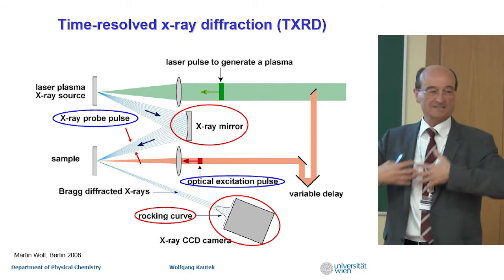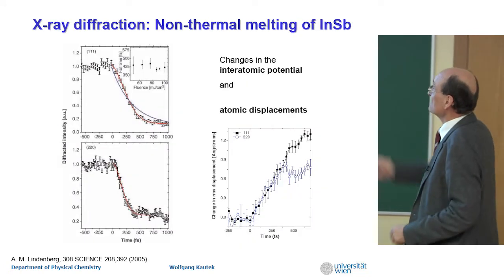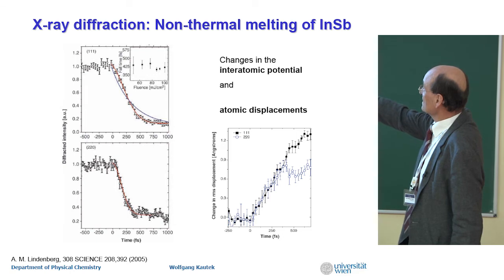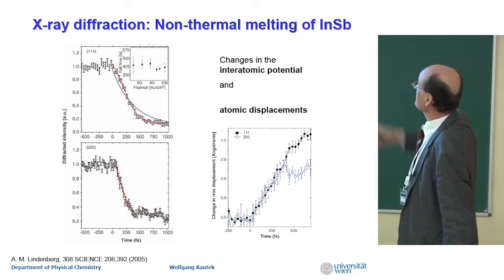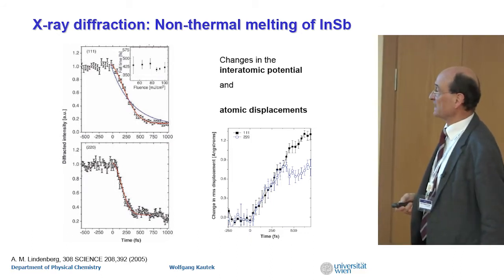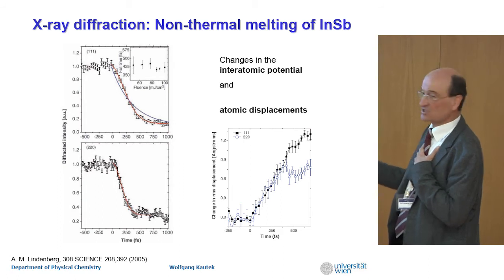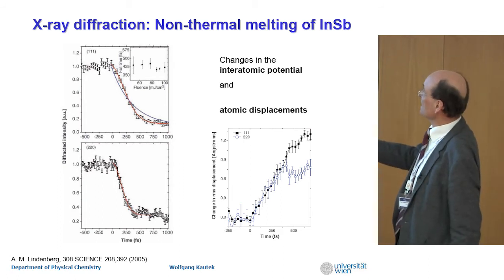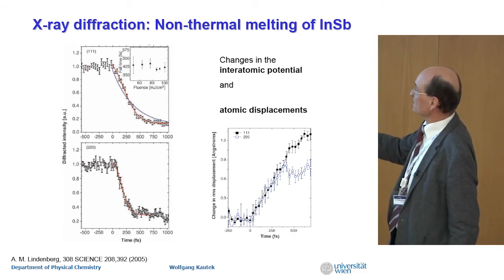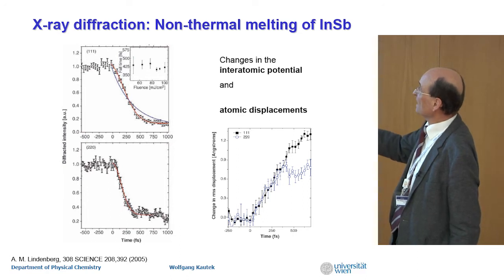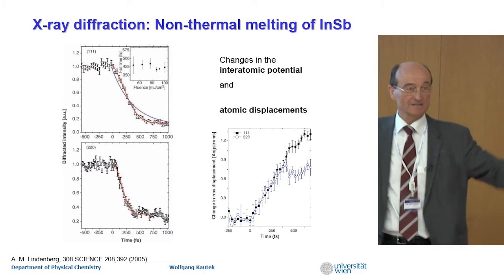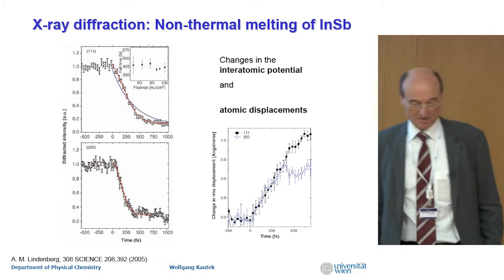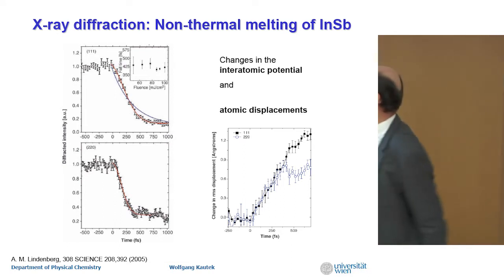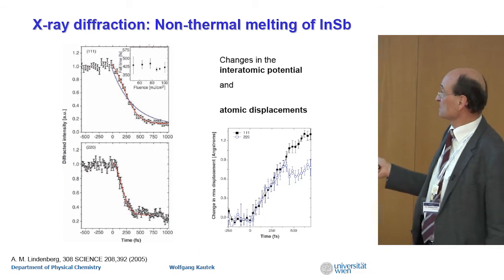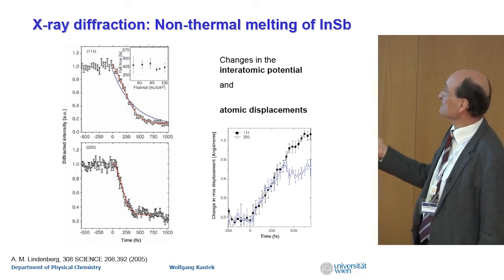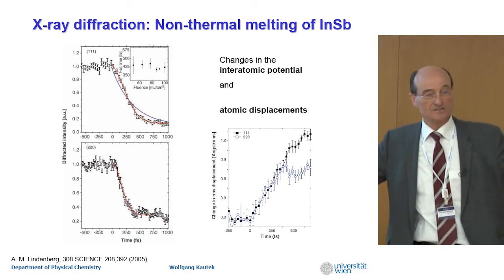And you see online that the material softens. Okay? There are such results, yeah, that the intensity of a peak or the broadness changes. So there is a softening of the lattice, and you can understand that if you plot, for instance, the potential energy of a single atom, before and after the excitation, the non-thermal melting. You have a broadening, and of course the distribution of displacements of atoms is widening. So the atoms have more possibility to move and then freeze again. You can calculate it also like this. We did experiments, and Mr. Garcia calculated and could show that a silicon lattice actually has a little softening and then freezes again.